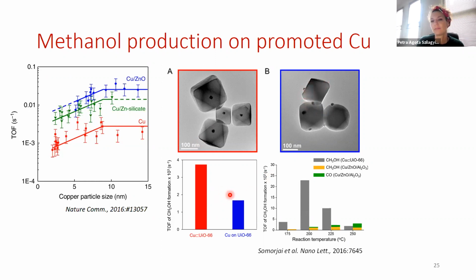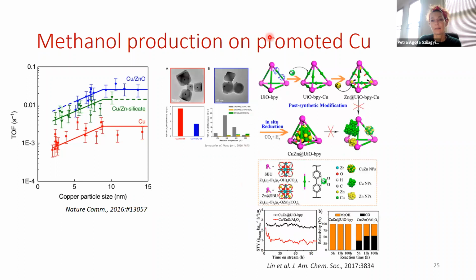They found that from just this difference in copper versus MOF location, the performance was significantly different in the 2 cases. Both activity and selectivity were very different. So the MOF does somehow contribute to this reaction as well. Then this other work came out in which they used the same topology, but replaced the terephthalic acid with this bipyridinic dicarboxylate. You can see the linker here, which elongates the pore slightly, but the overall structure remains the same. When they pinned zinc ions on the pyridinic nitrogens, that facilitated the assembly of copper nanoclusters inside the pores of the framework, and they found that this catalyst performed really well.